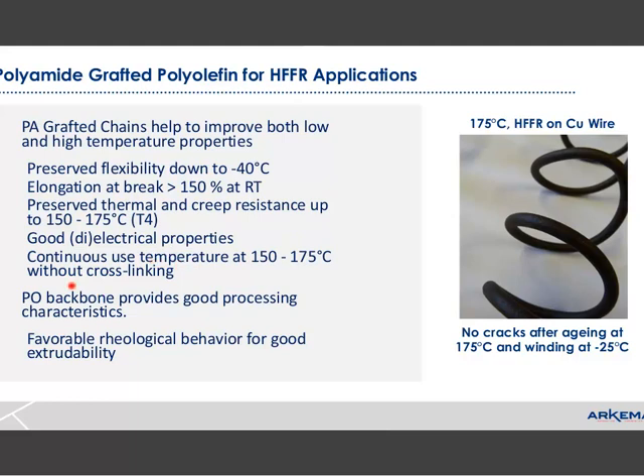The PO backbone, the polyolefin backbone, provides good processing, and it has very favorable characteristics. This over on the right, this was a test. It was 300 hours at 175 degrees C, and after winding at minus 25 degrees C, we see no cracks. So the overall properties are very, very good.